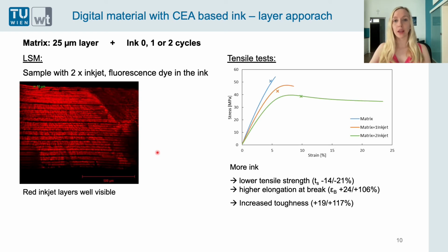And we also did tensile tests to see if it is possible to toughen the matrix material. And you can see here, the higher the amount of ink, the lower the tensile strength, but it's only decreased by 14 or 21% if you add 1 or 2 inkjet cycles to the matrix material. But the elongation at break can be increased much more, by 24 or 106%. And since the elongation at break increase is higher than the tensile strength decrease, it was possible to increase the toughness by 19 or 117%.